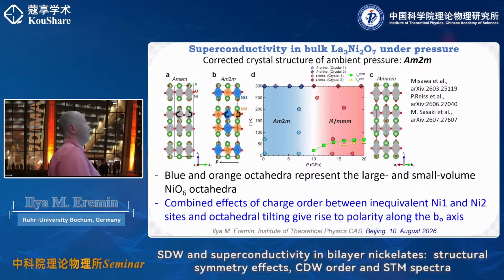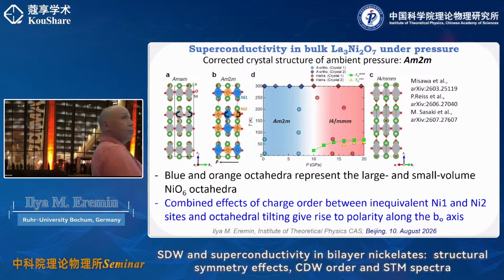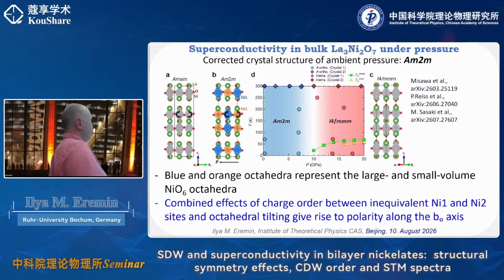There has been one paper by the group of Hirschberger from Riken. There has been recent data, which is just one month old. One of them is coming from Tokura group, also from Riken, but they grow very nice single crystals. And there is also the Stuttgart group, which has found similarly the same issue, that the actual symmetry is lower than Amam, and the symmetry is Am2m.